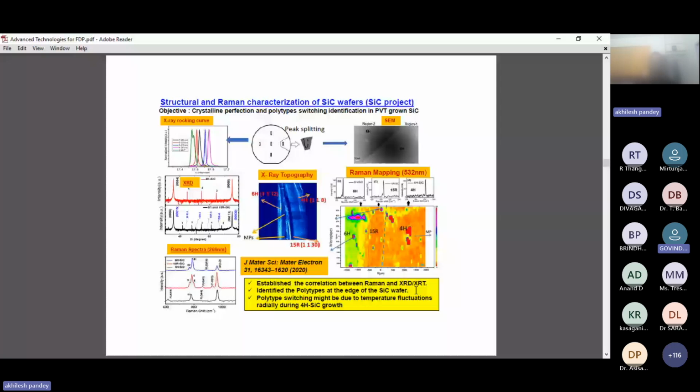In the X-ray diffraction gonio scan, theta-2theta scan, it was found that the 004 and 008 peaks are clearly showing. But apart from that, three intense peaks of smaller intensity have been identified. These peaks are related to 005, 006, and 007, and they are equally spaced. Kinematically, these peaks should be absent, but we still get them, because silicon carbide is a periodic structure, a natural superlattice type of structure. That is why these peaks are shown.